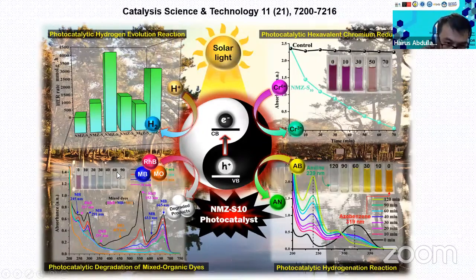So you see the time is only 1.5 hours, right, under solar light illumination. So all the peaks for MB, MO, RhB, and MO are all degraded. Then the last application is for the chemical conversion. We also found out that this can be used to hydrogenate azobenzene into aniline. As you see from this figure, the color of the yellowish azobenzene changes to colorless, and so the peak of the aniline comes out during the UV-visible spectroscopy analysis.